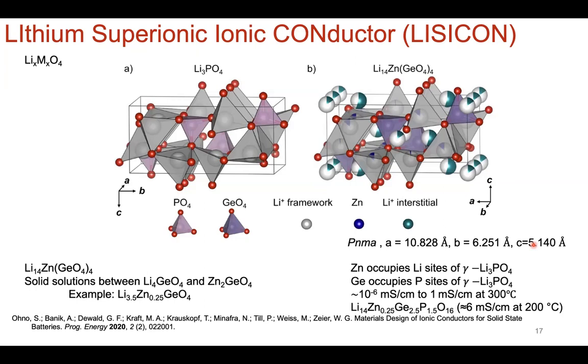Okay, so that is the distinction for why I keep saying high ion conductivity, although you've seen a lot of these materials discussed within the realm of superionic conductors. In terms of building up to thio-LISICONs, which are some of the compounds with the highest ion conductivities at room temperature seen for ceramic solid electrolytes, we first start off with LISICON-type materials that have these base compositions and structures. So lithium phosphate, Li3PO4, is potentially a relatively high ion conductor, although I would say it's medium at this point.